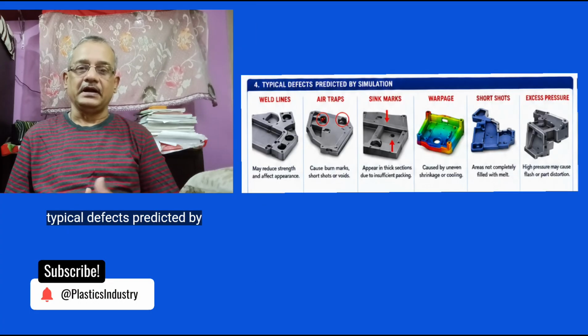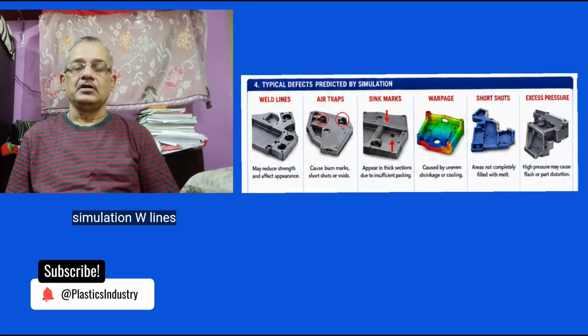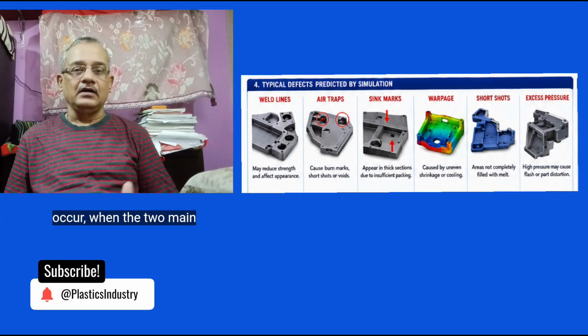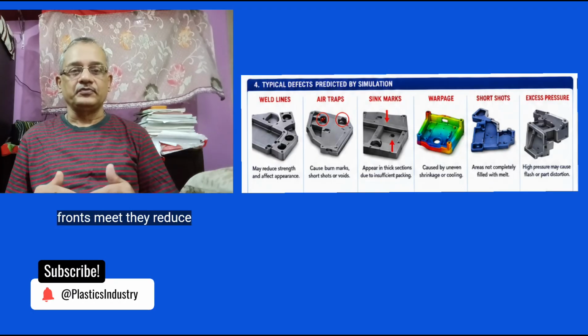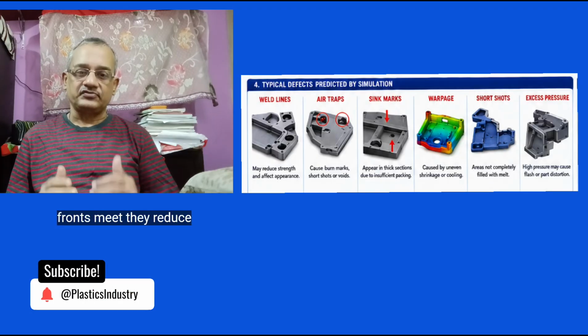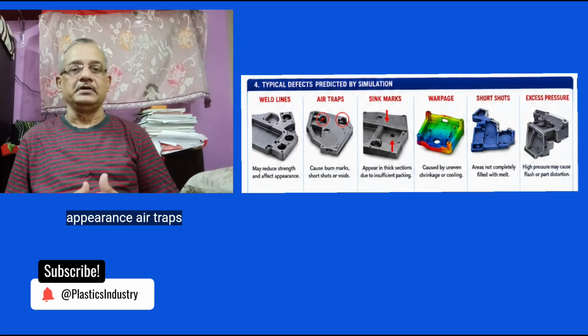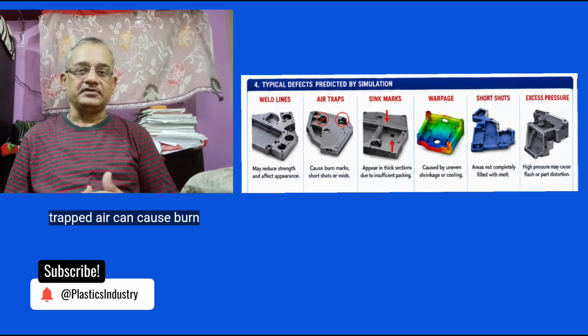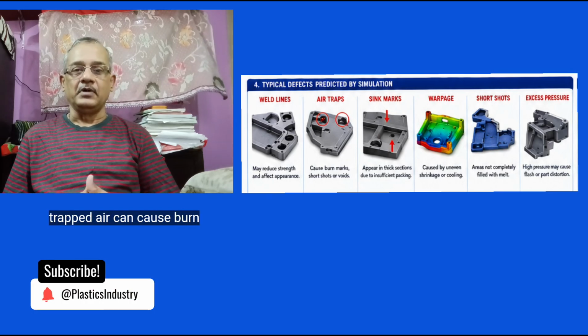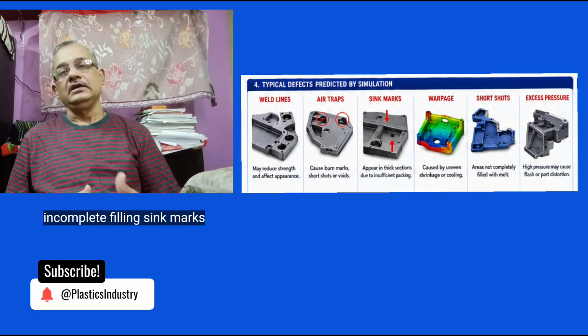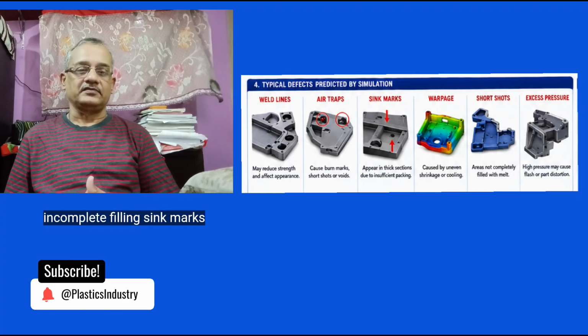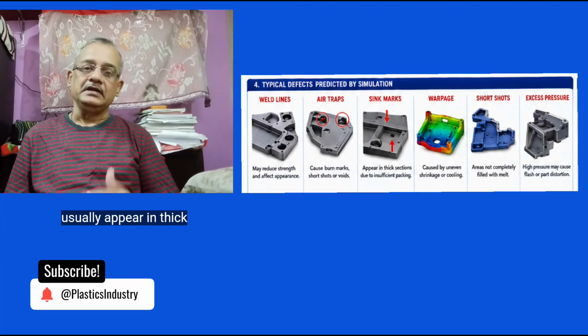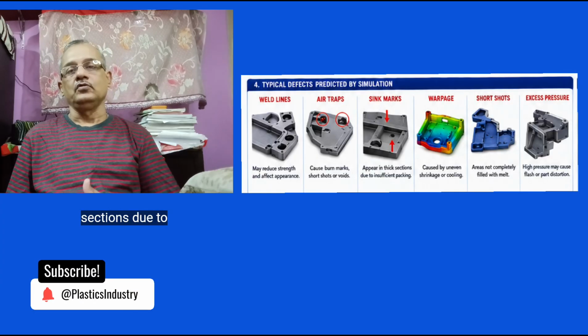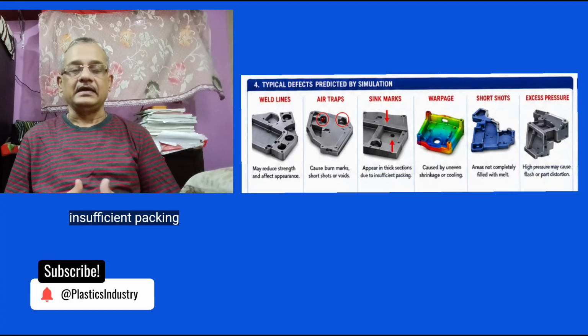Typical defects predicted by simulation. Weld lines occur when two melt fronts meet, may reduce strength and affect appearance. Air traps: trapped air can cause burn marks or incomplete filling. Sink marks usually appear in thick sections due to insufficient packing.